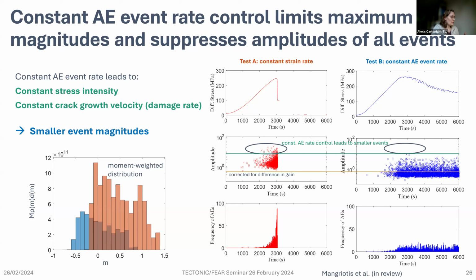which also helped shield them electrically. But yes, we used a high gain. We used a gain of 60 decibels in our constant strain rate experiment, and then increased it to 70 decibels in our constant AE rate experiment because of the signal to noise ratio in the acoustic data. So we had to correct all of the amplitudes on the constant strain rate experiment up, as if they were acquired with a 70 decibel gain, in order to compare the two.